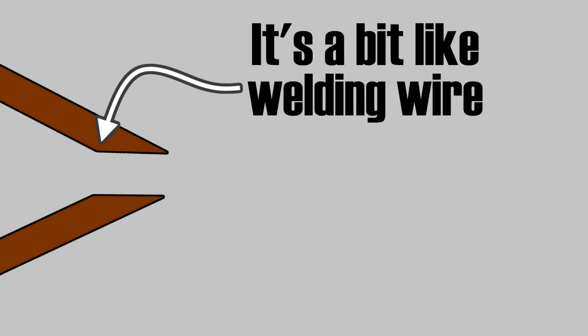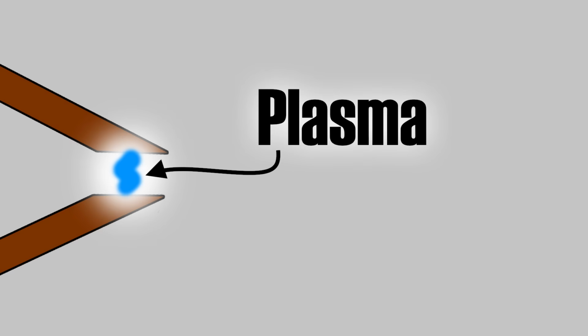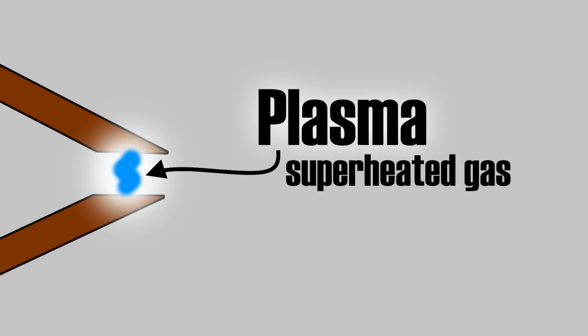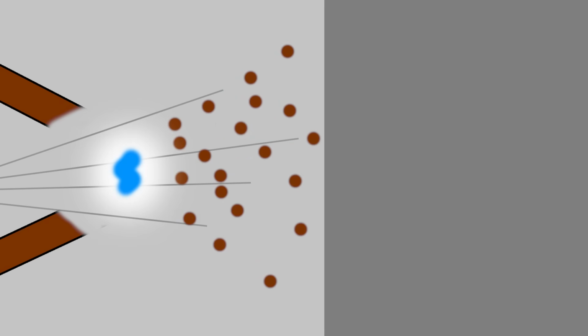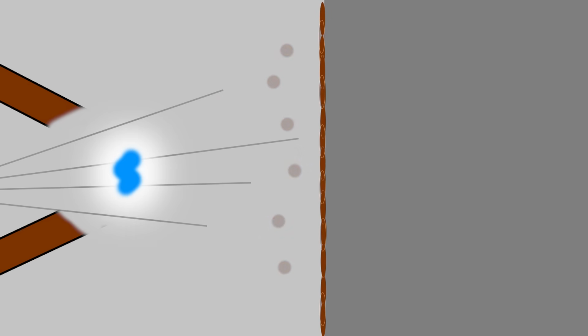We pass a ridiculous amount of electricity through these wires. The electricity arcs from one wire to the other, just like a spark plug, but much more intense. This arc is essentially plasma. It's a superheated gas, a high-energy state of matter. This incredibly hot gas then starts melting and atomizing the wire into tiny droplets. When that starts happening, we use another gas, either compressed air or nitrogen, to push, carry, and deposit these droplets of molten metal onto the cylinder. The droplets splatter, instantly transfer heat away, and solidify on the cylinder as a special coating.